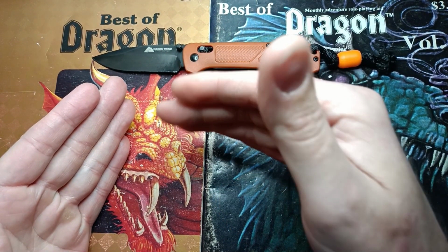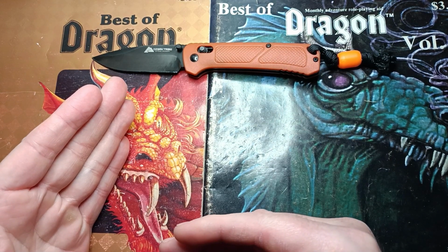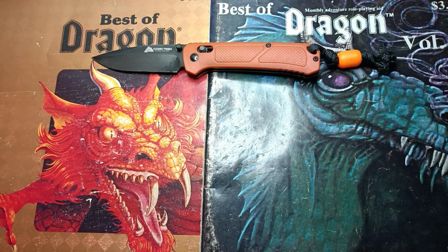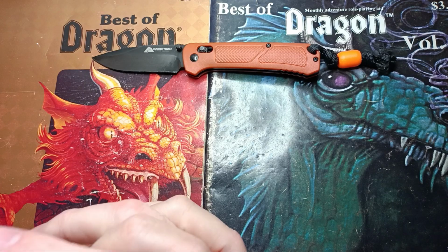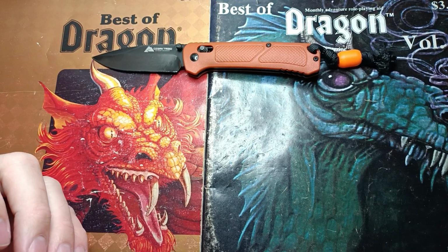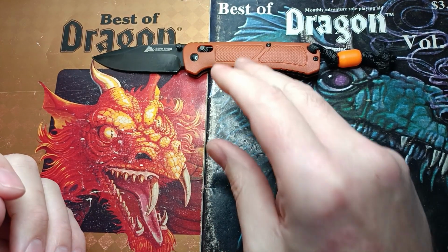And again, that number is so impressive because every other D2 we have done has crapped out at almost exactly the 4-hour mark every time. The O-Knife D2 seems to be a little bit soft. That crapped out at 3 hours and 30 minutes. But again, very consistent results. That's part of why I freaked out so hard about this. And it was not just one, but two.